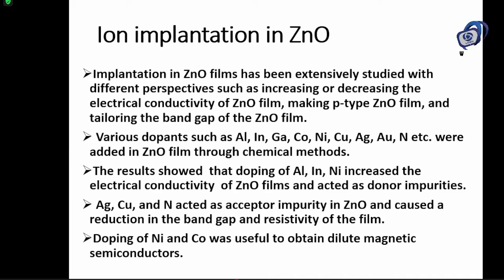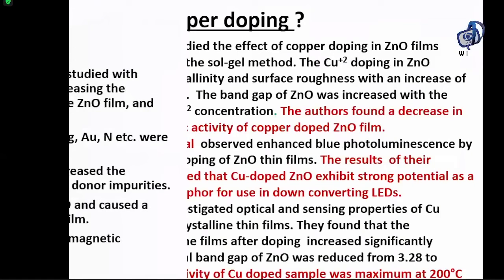We implanted various kinds of metal ions: aluminum, indium, nickel. And here we have used silver, copper, and nitrogen because they act as acceptor impurities in zinc oxide, and they cause a reduction in the band gap and resistivity of the film. Nickel and cobalt were useful to obtain dilute magnetic semiconductors. I'm giving only one example, which is the copper doping.